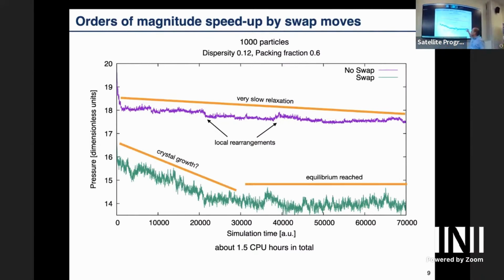And what you also see here is that now we see this almost linear slope, and then it becomes constant. So what's actually happening here, there's crystallization happening now in this polysphere system with these swaps. So now with swaps, you can access times that are much, much longer. Depending on the density, they can be 6 to 9 orders of magnitude longer than what you can get just without the swaps. That's also what Berthier and others in the glass community are utilizing to relax their glasses, and then we have some equilibration here.